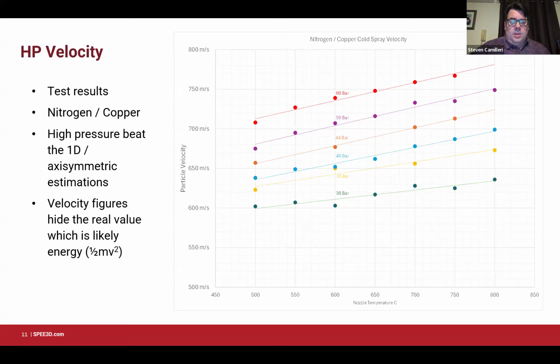happening. So those of you that have had a good look at the velocities on the left here will say, well, actually, there's not a significant increase in velocity, like the number of meters per second only increased by 15% maybe over the whole spectrum here. Is that really that much? And the short answer is, well, yes, it is. So the factor that actually seems to impact cold spray more than velocity is the kinetic energy, which is a factor of velocity squared. So we see quite a lot of improvement in the effective kinetic energy through this diagram.